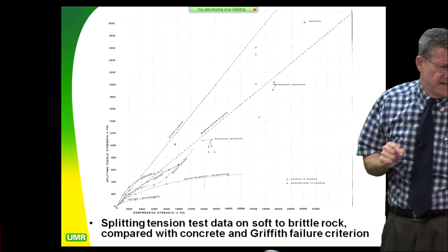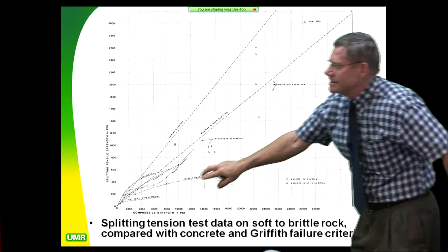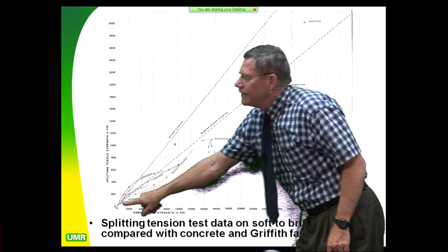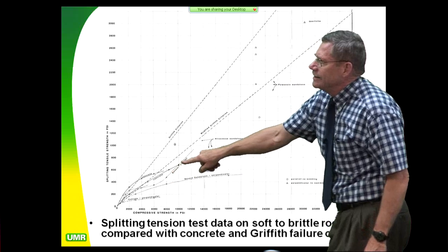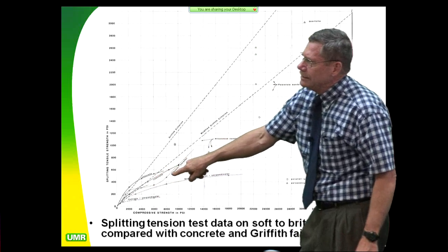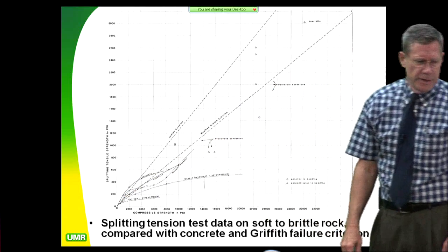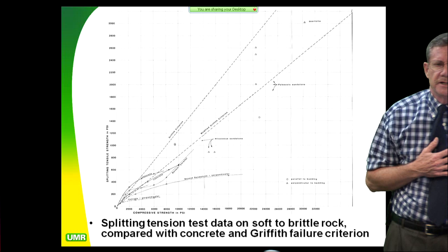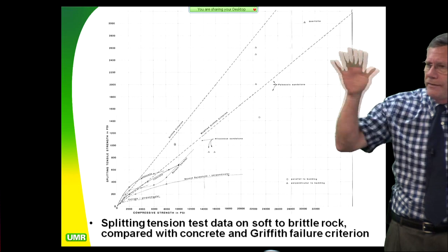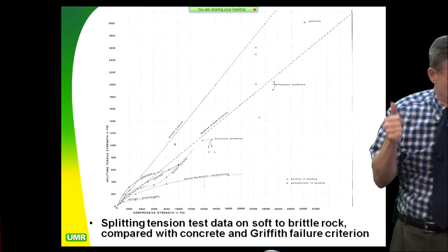Now, if we look at all the ACI, the American Concrete Institute data out there, it's pretty interesting. What you'll see is these little curves down here, that one is the upper bound for concrete, and this one is the lower bound. And you see the lower bound one's below 1/12, but 1/12 cuts right through the mean of those two families of curves. That's where all the data is, thousands and thousands of data points. So we know that. That's out there in the ACI literature. There's an article by Jerome Raphael, I think about 1979, in the ACI Journal, where he took all the tensile data for concrete around the world and plotted all of it. So it's a great, great paper to have on the shelf.